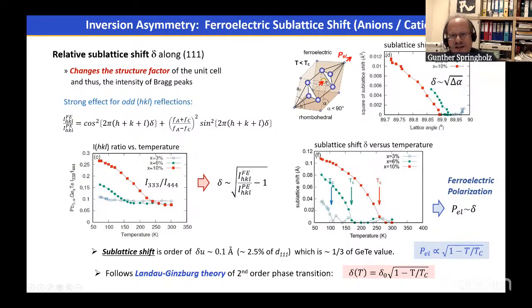So this sublattice displacement can be measured by measuring the intensity of odd Bragg reflection as a function of temperature, as is shown here, and one can see that with increasing germanium concentration, there is a deviation from a constant value of this intensity ratio, and this deviation from this constant value is the onset of the ferroelectric phase transition. But one can also quantify this sublattice shift by evaluating this intensity ratio using this equation here.